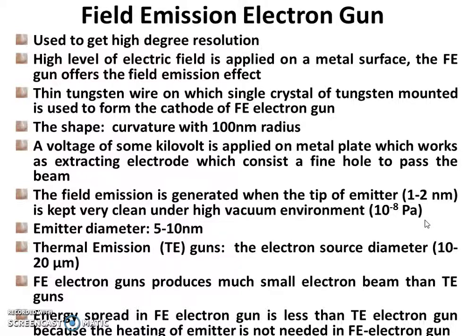These electron guns are used to get a high degree of resolution, and a high level of electric field is applied on a metal surface. The FE guns offer the field emission effect accurately and cleanly. A thin tungsten wire on which a single crystal of tungsten is mounted is used to form the cathode of the field emission electron gun. If you talk about the shape, the curvature of such electron guns makes a 100 nanometer radius. A voltage of some kilovolt is applied on a metal plate which works as the extracting electrode, which consists of a fine hole to pass the beam.